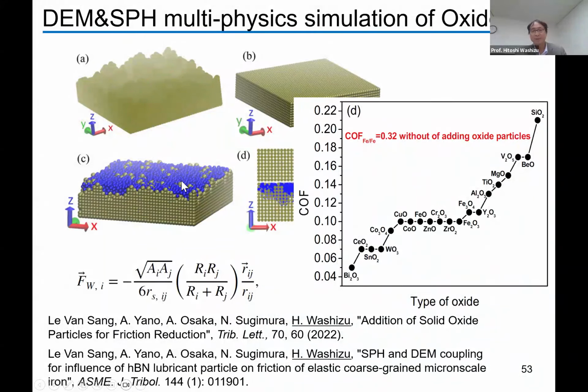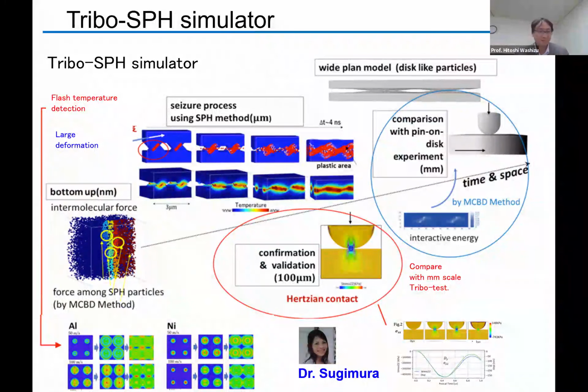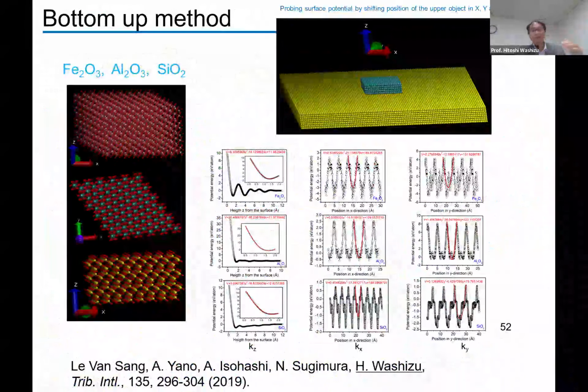And sometimes we put some particles here for lubrication, and then we rub here, and this is the change of the friction coefficient with adding some oxides. We put some here, and we can reproduce the sequence of the material difference by this simulation. All right, but the last topic is about much more wear, much more seizure, and much heavier conditions.